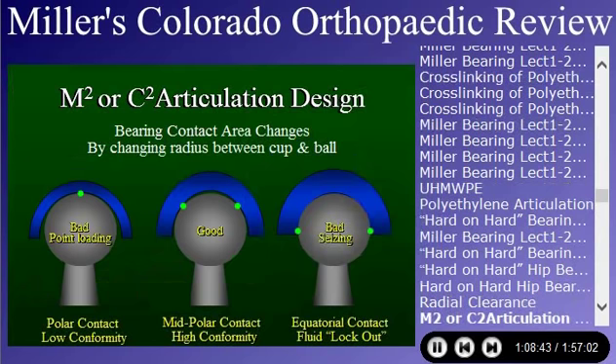What we learned in the past is that if you look at the left, if you had a radial clearance which was too much of a difference, you had point loading, and you would have what we call polar contact and low conformity, high stress loads, and that would cause sliding wear and scratching and wear. On the far right, you would have what we call equatorial contact. The contact was at the equator. There was no fluid going in there, and these would seize up and it'd have a high frictional torque.